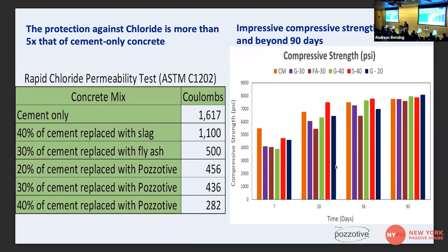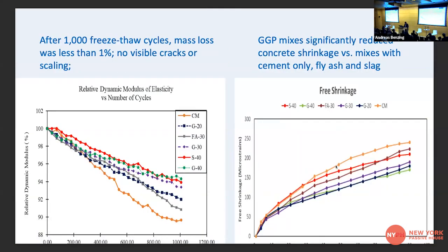With regards to compressive strength, it quickly catches up to straight cement in the mixes as well, and it continues to grow in strength past 90 days. With regards to freeze-thaw studies, again, this was done by City College of New York. What you see here is a 1,000 cycle freeze-thaw study, and it shows that you had less mass loss in your beam. So over 1,000 cycles, no visible cracking, no visible scaling, and that's amazing because that adds to the life cycle of that concrete. You're making a more durable, longer lasting concrete when you use ground glass pozzolan.